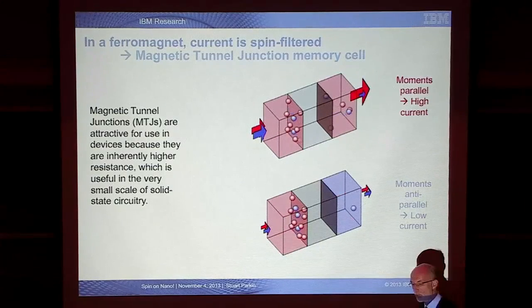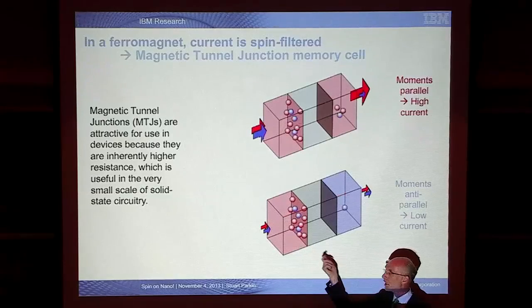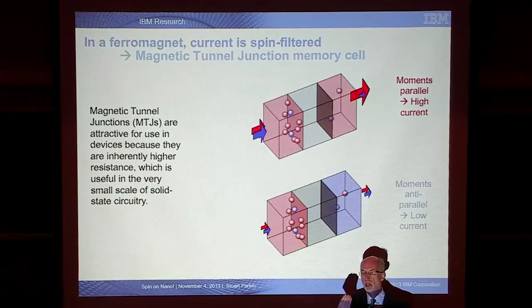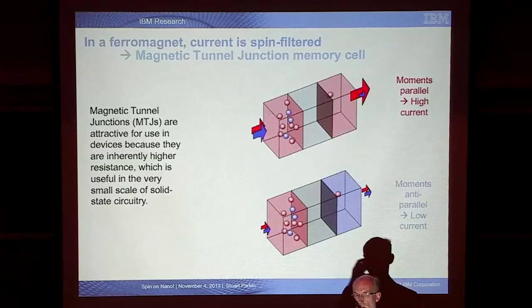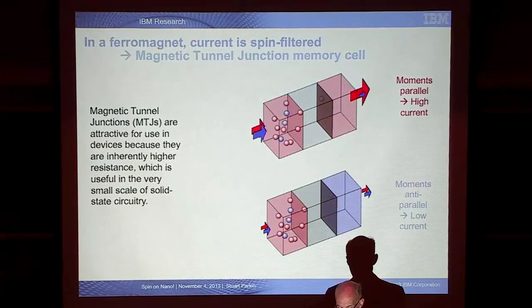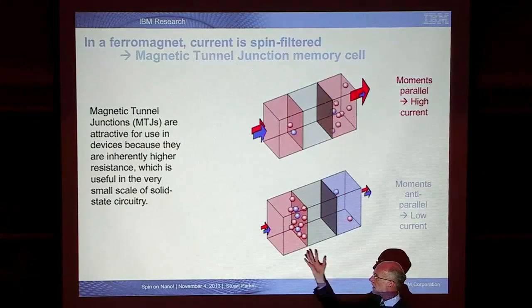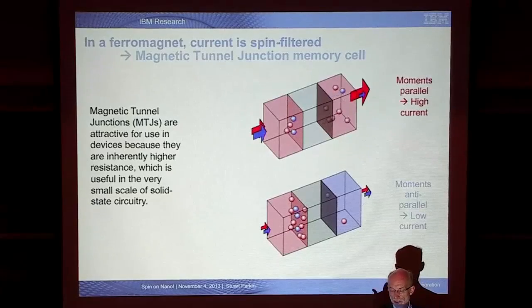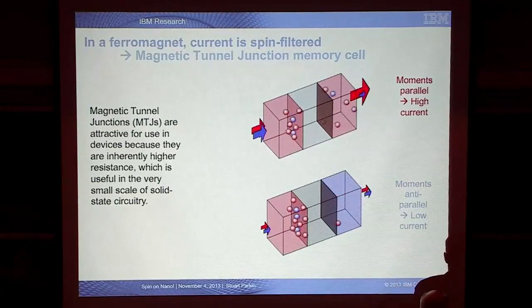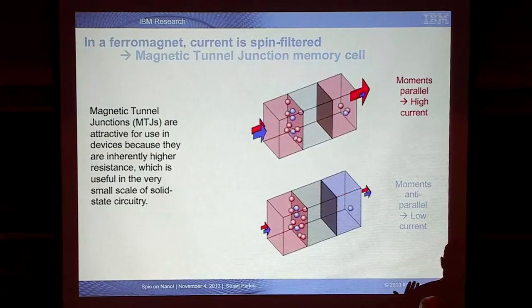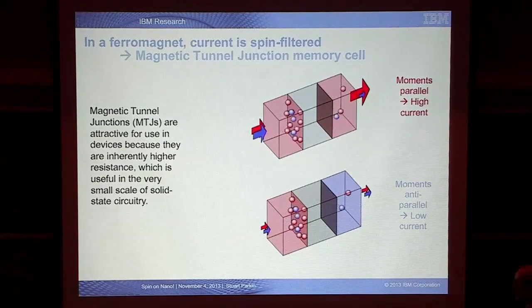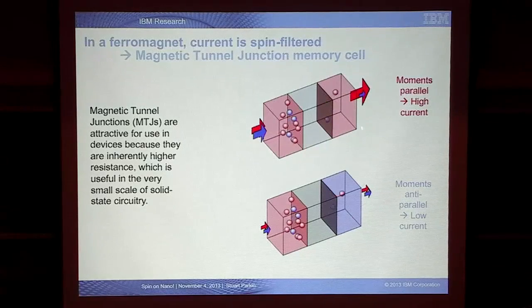It was known for many years, since the 1970s, that if you extract current from the surface of a magnetic material, the current will inevitably be spin polarized, and you will extract more electrons of one spin orientation than the other. This is fundamentally because of the magnetism of this material, and the electronic structure now breaks symmetry, and there will be more electrons of one spin orientation than the other at the so-called Fermi energy from where the electrons will tunnel. If these magnetic layers are parallel, then electrons can readily tunnel from states which are spin polarized in one direction to empty states of the same spin orientation. During this tunneling process, the spin of the electron will be conserved. It's a very short process.